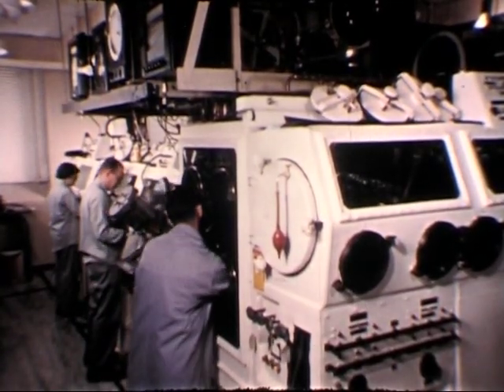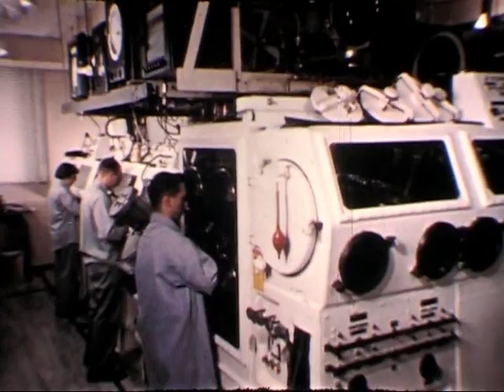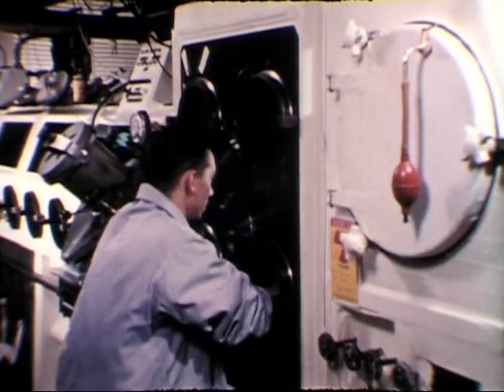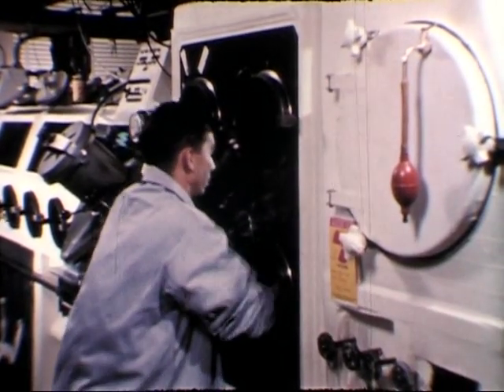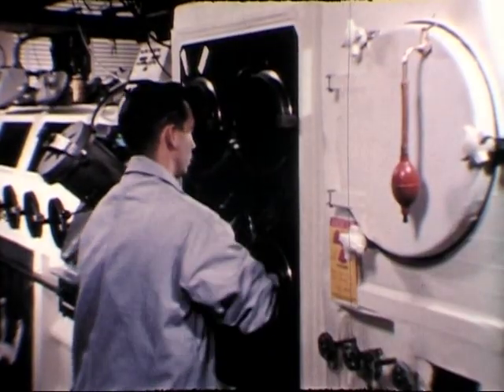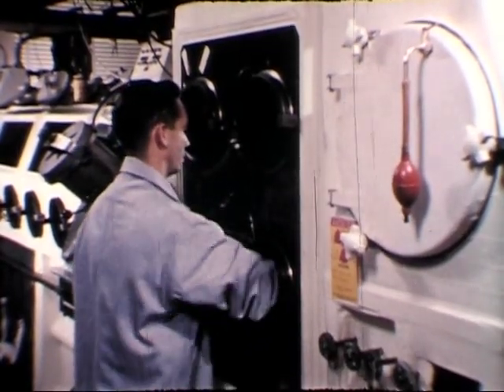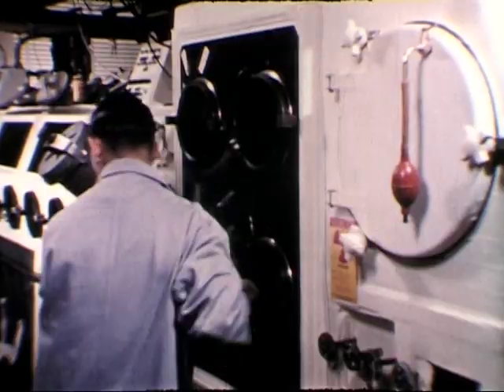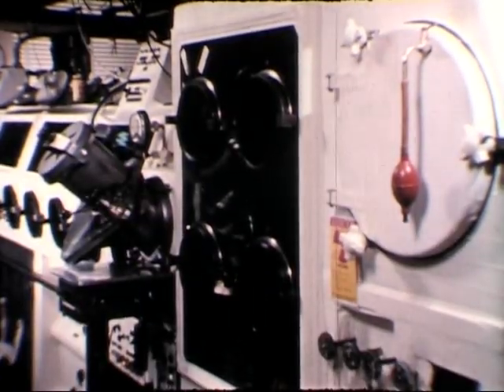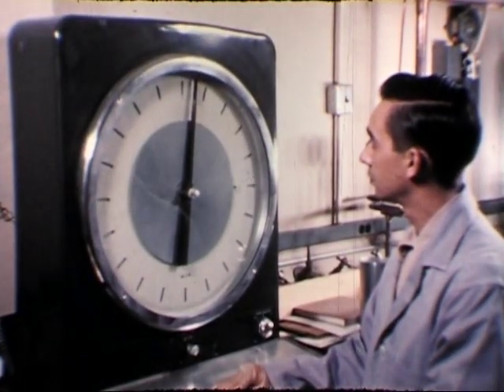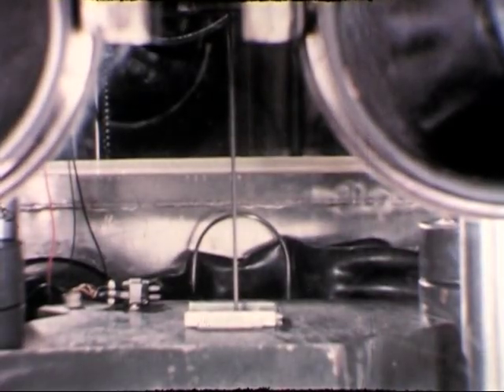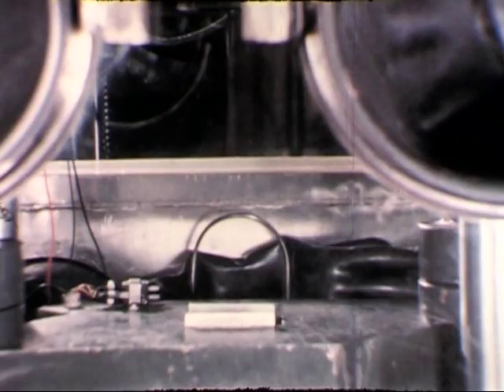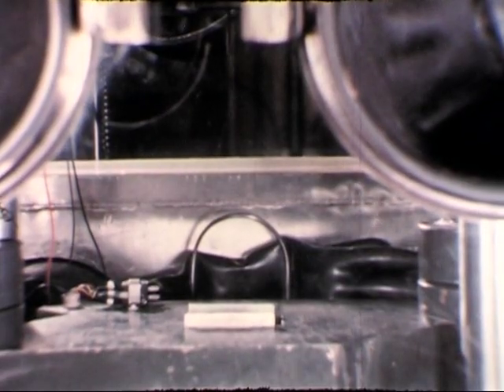The desirability of fueling reactors with plutonium has required investigation into the mechanical and physical properties of plutonium alloys. This facility, designed for complete containment in an inert atmosphere, permits studies of properties and fabrication of plutonium-containing materials with a minimum of hazard. The range of plutonium concentration in alloys studied has been from 10 to 30 weight%.